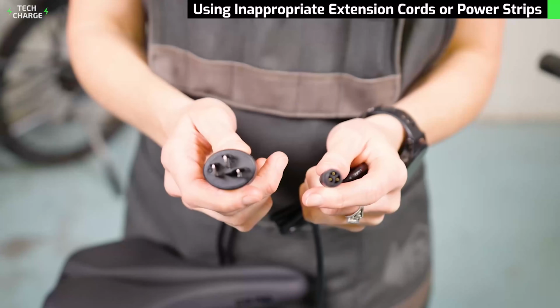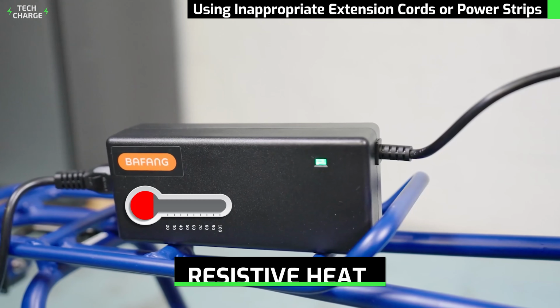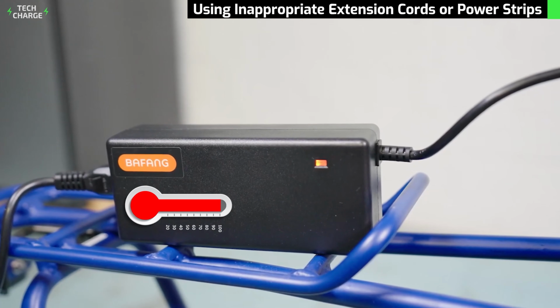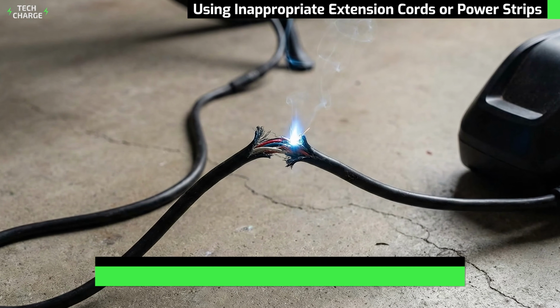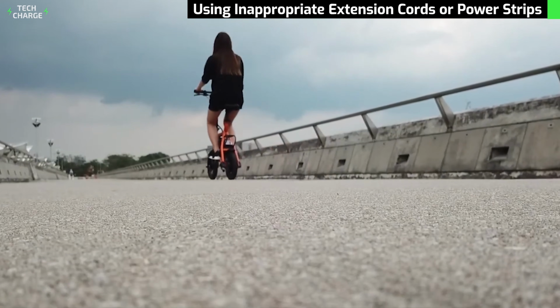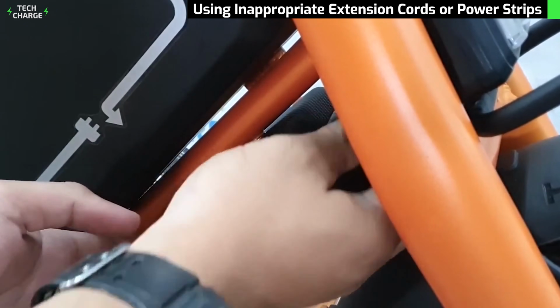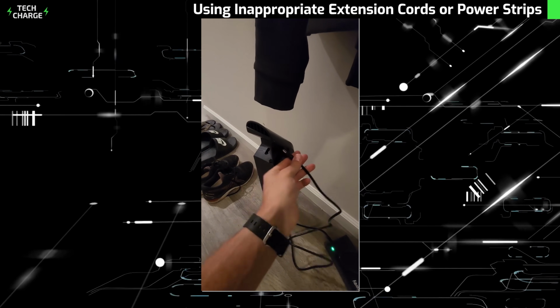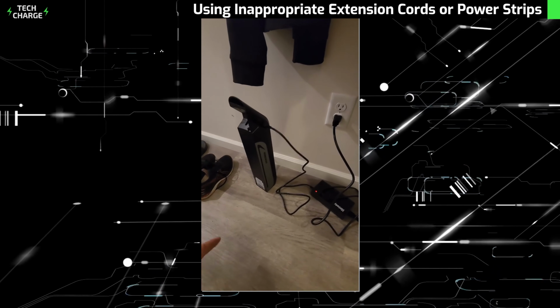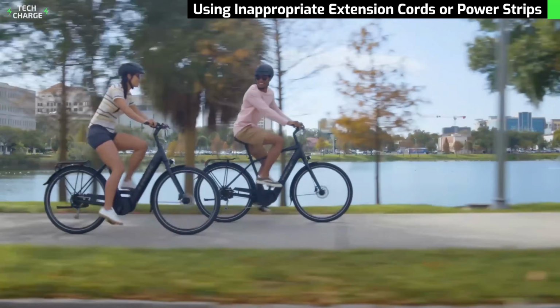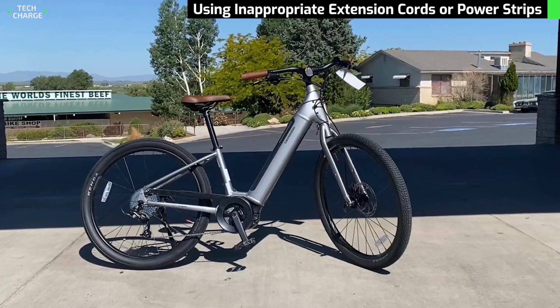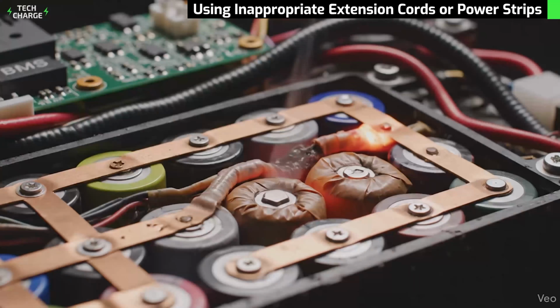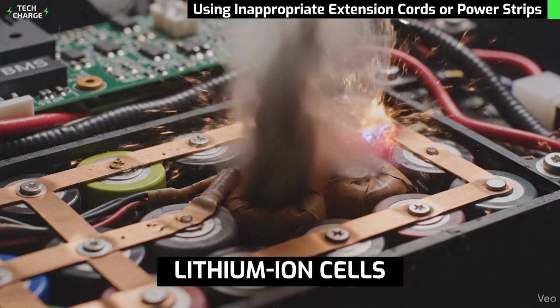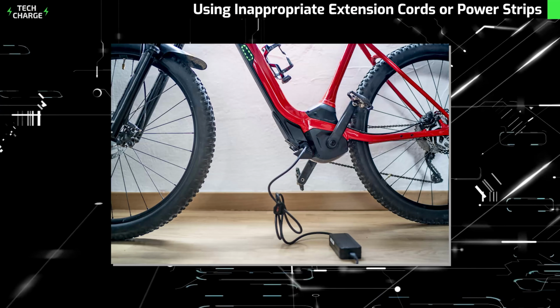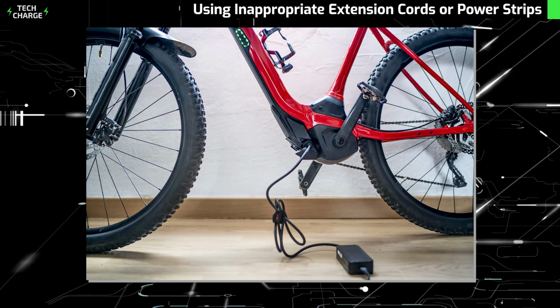Here's what happens. Thin or unrated extension cords generate resistive heat when high current passes through them over extended periods. This overheating can cause the cord itself to short circuit or catch fire. But there's an even more dangerous secondary effect. The external heat generated by a failing cord or power strip gets transferred directly to the battery charger and potentially the battery pack itself. This proximity to an external heat source accelerates the internal heating process within the lithium-ion cells, potentially triggering thermal runaway, even if the battery chemistry is completely stable.